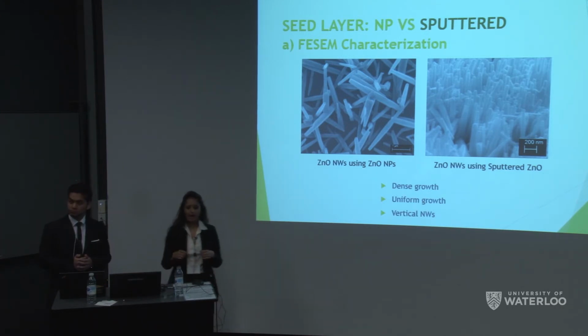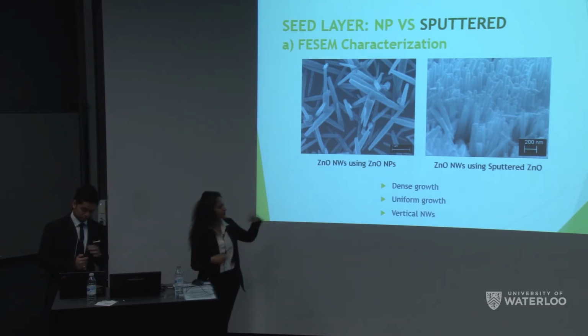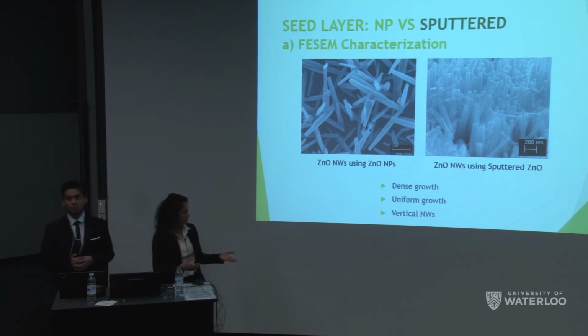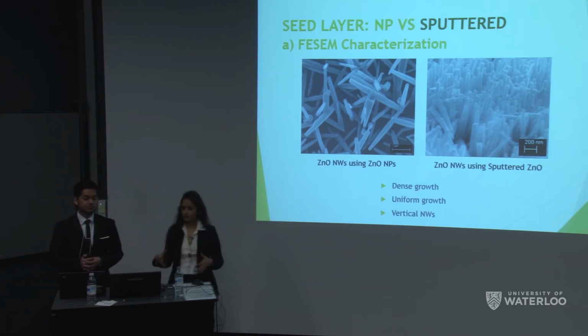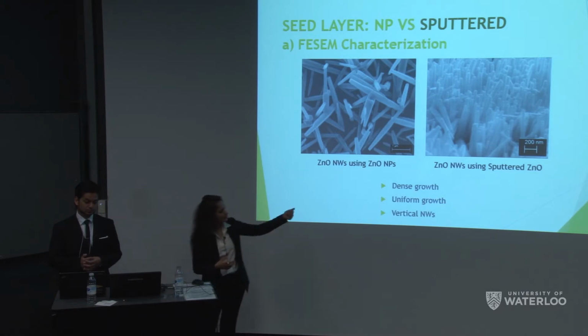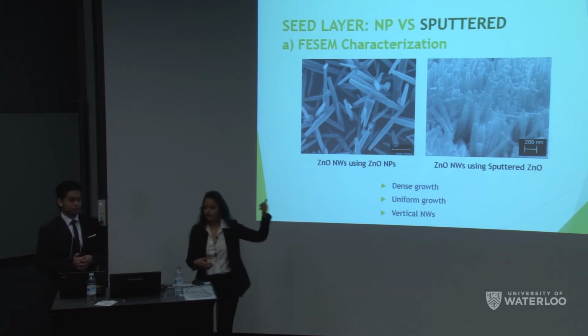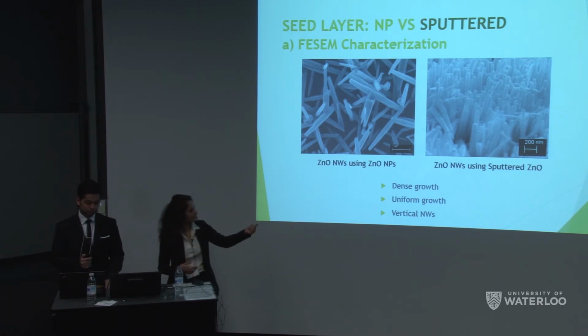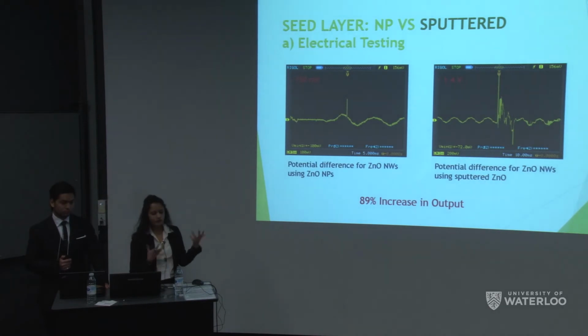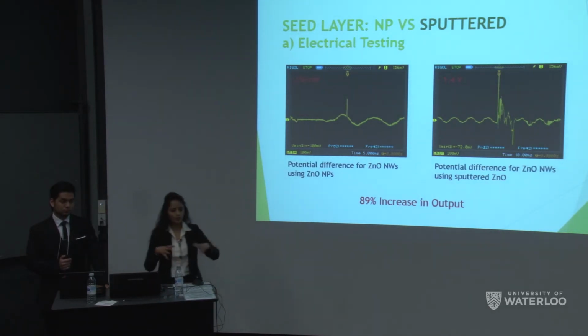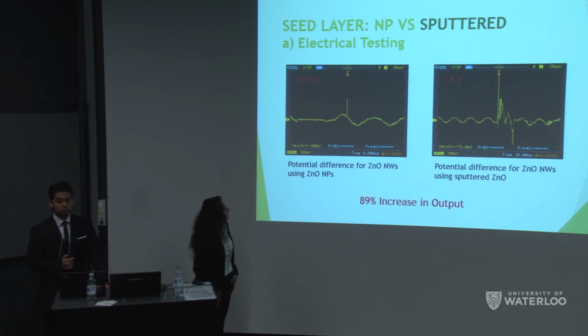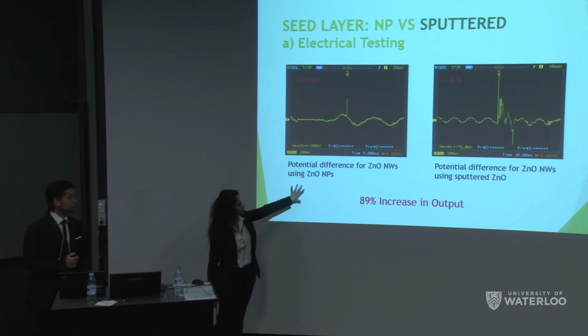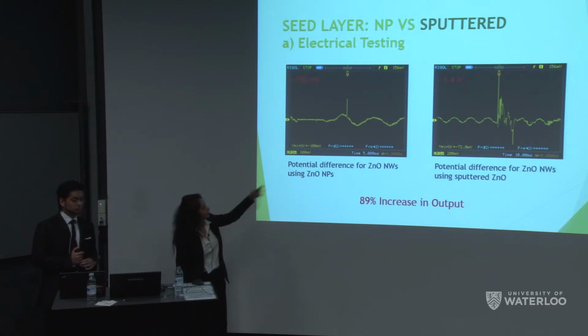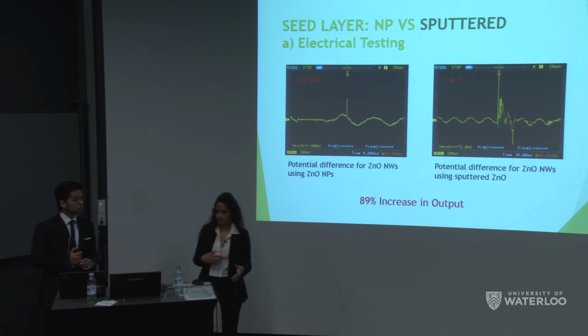So for this method, we had two approaches that we could have used. One was just spin coating some zinc oxide nanoparticles, and the other was actually RF sputtering a thin seed layer of zinc oxide. So again, we tried both to see which one would work better for our device. And as the images show here, the sputtered zinc oxide seed layer gave us much more vertical, uniform, and dense growth of wires. And even the results reflected that. We exposed both the devices to a mechanical stress by tapping on them, and we measured what electrical results we would get. And it was evident that the device which was made with the nanoparticle zinc oxide gave us much lower results than the sputtered seed layer.